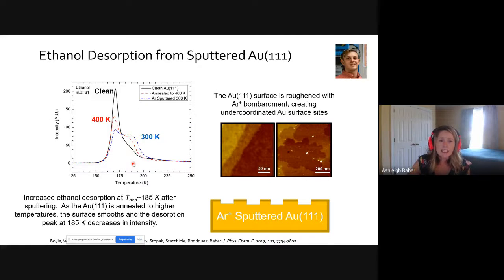If we sputter our gold 111 surface and form pits across the surface because of that roughening sputtering procedure, and then dose ethanol directly onto that surface and run a TPD, we can see that, in fact, we have increased the desorption of that higher temperature feature at about 185 Kelvin. That's represented in this blue dashed line here. Then as we anneal that surface up to 400 Kelvin, that will help to start to heal some of those pits within the surface. We can see that the intensity of ethanol adsorbed to those features is decreasing, but we're not fully getting rid of all of our steps. We do have a fairly stepped surface.